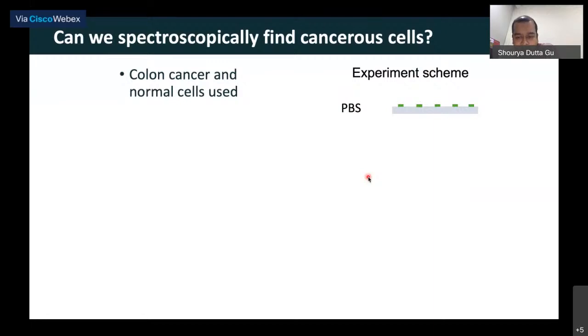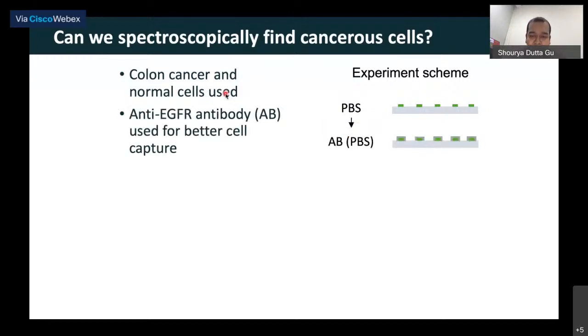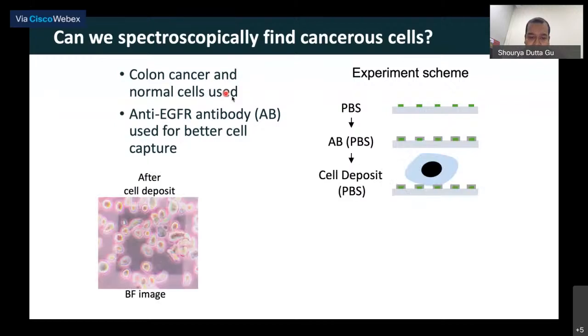This experiment was done in multiple steps. In particular, we use two different kinds of cells: colon normal cells and colon cancer cells, right? So we start with the metasurface, which is in buffer PBS. Then we put a layer of antibodies, which are basically used for capturing the cells that we'll put in the chamber. Then we allow the cells to get captured. This is a typical bright field image of the cells. Each of these blobs is a cell, and the dark gray region that you see is the metasurface. You see around 10 to 15 cells on these metasurfaces.